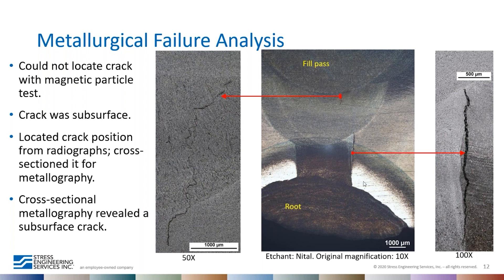The crack is in several beads. Metallography allows you to see all the weld passes — fill passes and root passes. The crack is separated along the solidification grain boundaries, which show a distinct pattern. It appears that this particular root pass was made from the inside surface of the slug catcher.